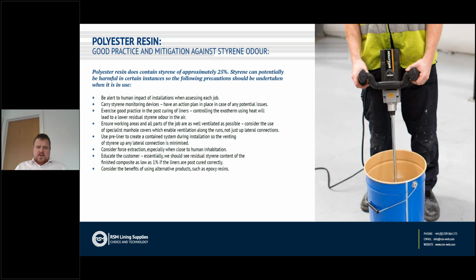The biggest thing that we can do to ensure that the styrene odour is minimised is to ensure that we have the correct post-curing of liners. Controlling our exotherm using heat leads to residual styrene odour being lower. And really, we should be aiming to have a residual styrene content of as low as 1% if liners are post-cured correctly.